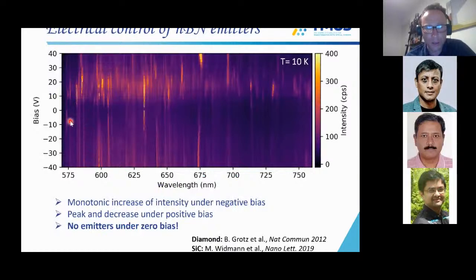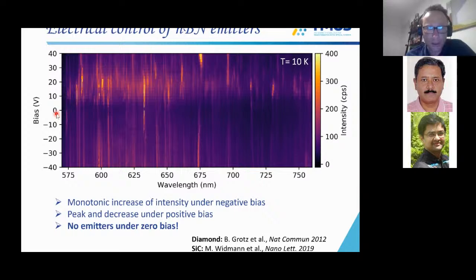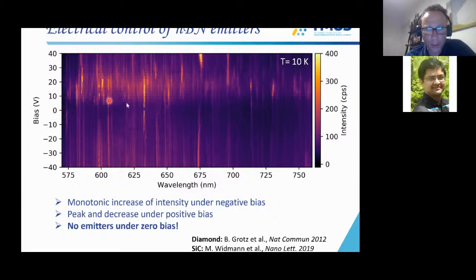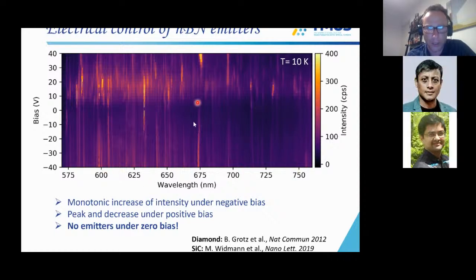So you can see here, and I'm sorry, this is a bit of a busy slide. When you cool the system down and you induce a large ensemble of emitters, you can see that at 0 volts, 0 bias, there is almost no luminescence. This is as a function of spectrum. There are many defects here, so every line is basically an emitter. And as you increase your voltage, you will see that the emitters turn on and then off again.